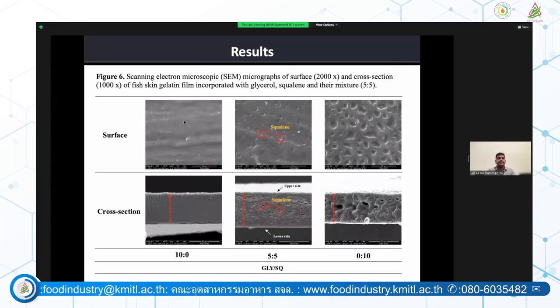So next, this is the scanning electron microscopy of the films. This is the glycerol film, and we could see there were no emulsion droplets distributed across the film. And the thickness of the film was a little bit higher in the emulsion films. And we can see there is a uniform, homogeneous distribution of squalene droplets in the film with the 5:5 ratio of squalene and glycerol.